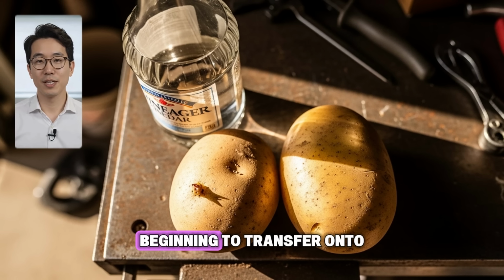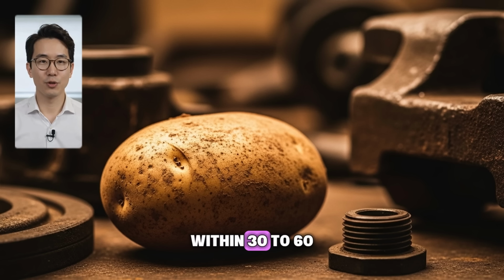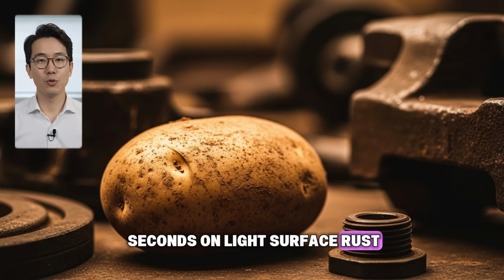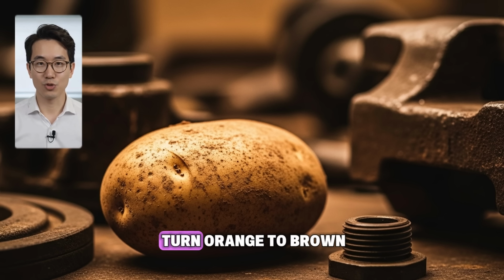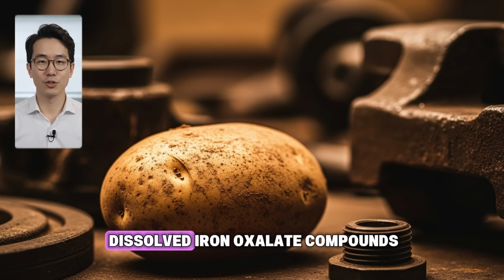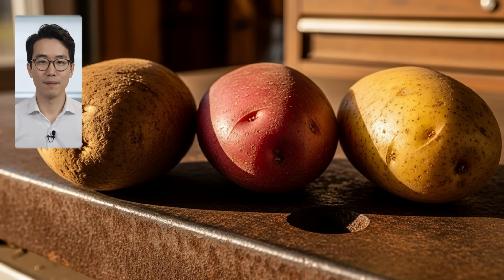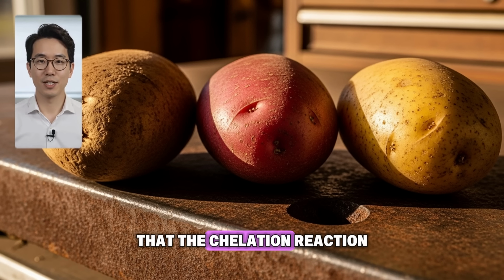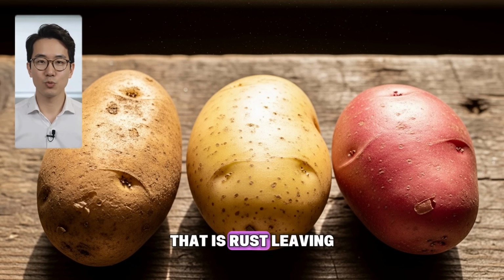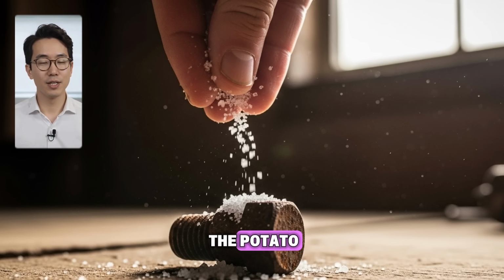You will see the rust beginning to transfer onto the potato flesh within 30 to 60 seconds on light surface rust. The potato flesh will turn orange to brown as it absorbs the dissolved iron oxalate compounds. This discoloration is evidence that the chelation reaction is occurring, that is, rust leaving the metal and entering the potato.